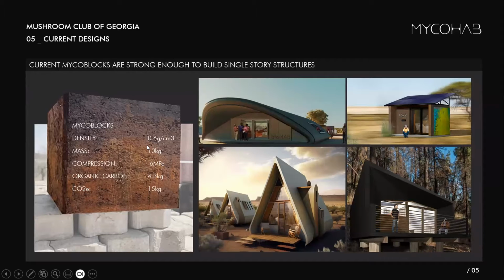It's a net storage. So these blocks are strong enough to do 1-story structures, and you see several of the designs that we have there. The one on the top right is obviously the one we looked at that is almost complete at this point. We have done arch structures in the past. They work, but they become quite a bit springy because they have this wood-like quality. They have this ductility to them that makes them good in some regards, but it doesn't work very well the same way that masonry units usually do in compression. It's more like a woody material than it is a masonry material.